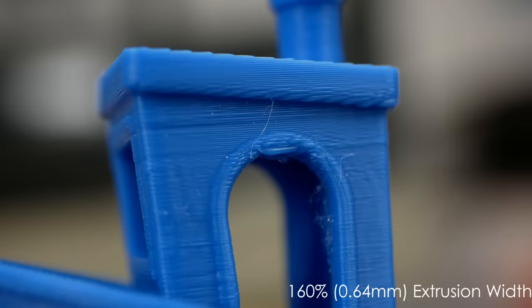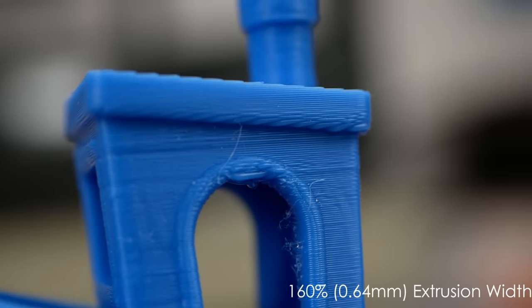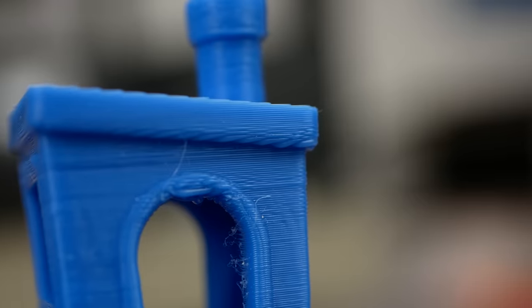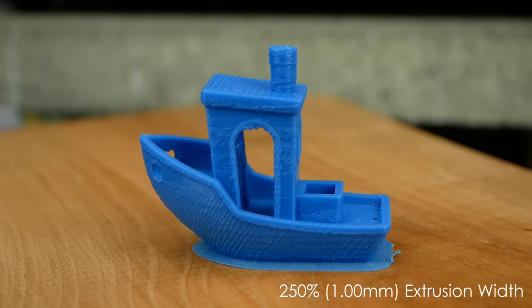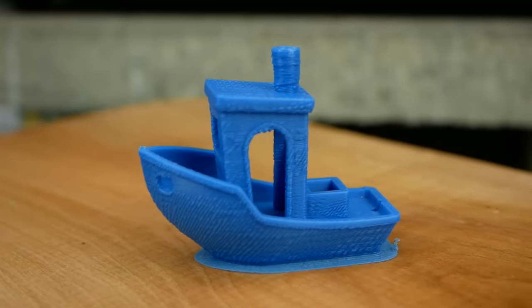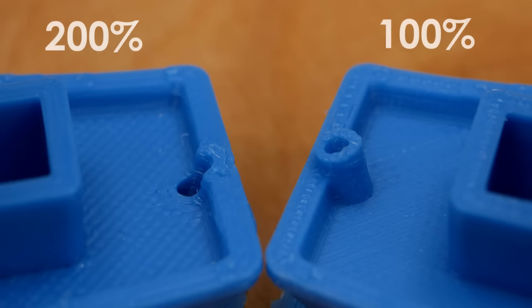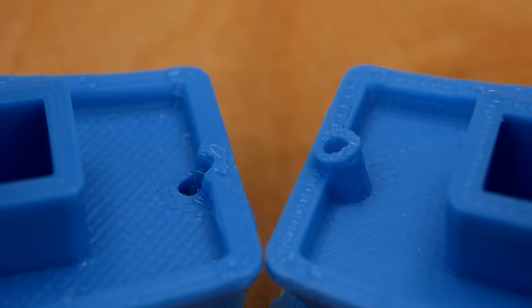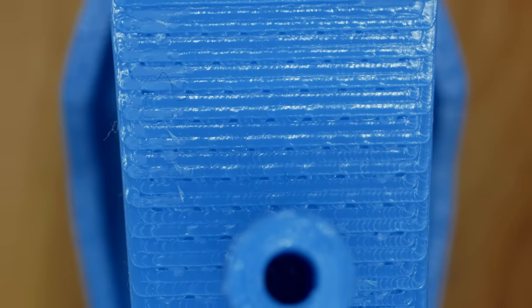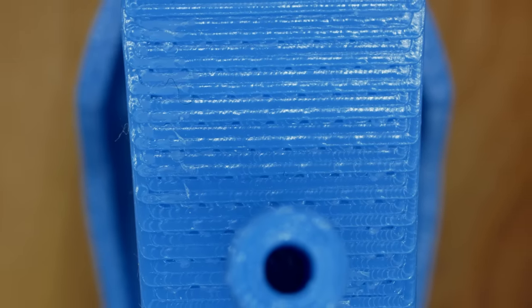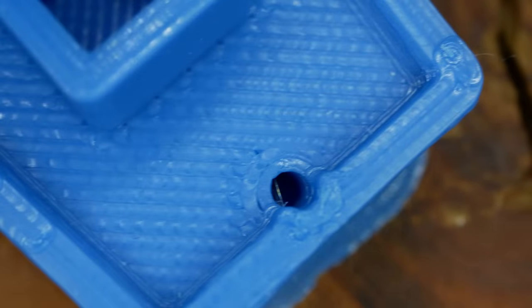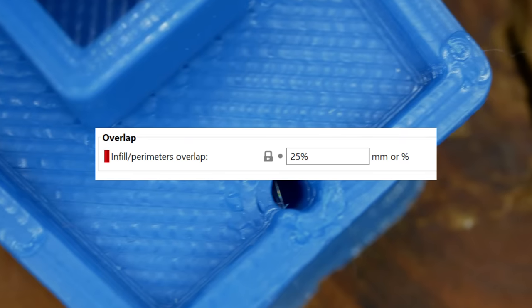At 160% I was slowly able to spot artifacts in the overhanging regions, probably because the material is squeezed out that much. At 250% the whole surface was even strangely textured. At 200% and higher, the flagpole base just vanished not because of printing problems but because the part just had two thin walls to be printed with a 0.8mm extruded line. At higher extrusion widths, some areas looked as if they were a bit underextruded, though I think it was only the overlapping areas with the perimeter that needed tuning.